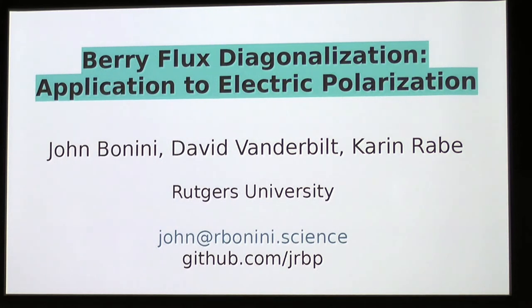I came back to the Electronic Structure Conference in May. They had a poster with a theory. I went back to Lausanne, and we started working with the Berry phase all of the summer. At the end of the summer, we had the very first calculation ever of spontaneous polarization. After you have converted a phase into Coulomb per square meter, then the nuclear part, then the modulo 2 pi, at the end, our number was within 10% of what we found in Landolt-Börnstein. That was the most exciting moment of my professional life.